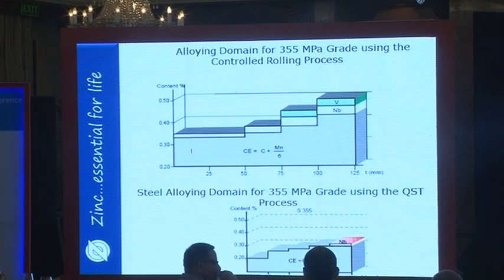And you can see, whereas in the old days, using the controlled rolling process, and even before that, we were required to put much richer compositions in to obtain the 355 grade. With the QST process, you can see the stair-step shape has dropped. We're no longer starting off at 0.35, we're starting off at 0.2 on the y-axis, and then we stair-step up even slower, because we're taking advantage of the metallurgical transformation behavior rather than relying upon the compositions that are shown here. This really shows how we've been able to make the steels lean if we do this.